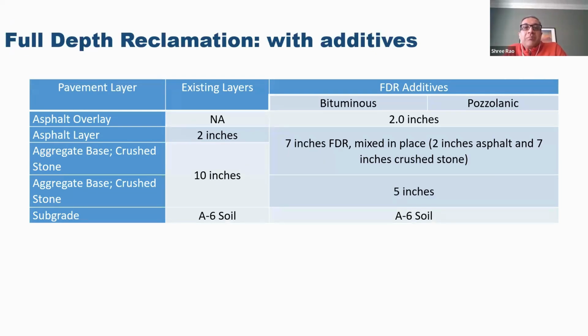Typically, if you do full depth reclamation, it is with additives. And so here's some example. The default or the baseline case is 2 inches of asphalt layer over 10 inches of stone. And then here's the full depth reclamation, 2 inches of an asphalt overlay. Again, this is just for comparison purposes. They don't necessarily mean that this pavement is a replacement or identical to this, but it's kind of close enough. Over 7 inches full depth reclamation, and then 5 inches of crushed stone aggregate base, and then A6 soil as the subgrade.